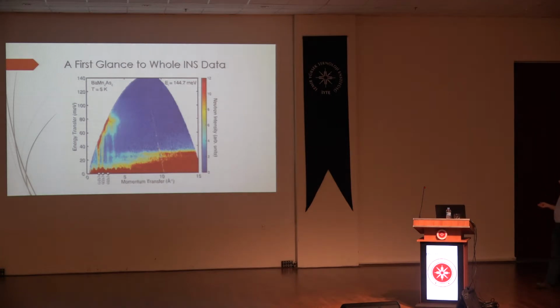First glance at the whole data. The whole data is this. As you see, that is three-dimensional data. This is not a point detector scattering experiment. That is an inelastic powder experiment, where the detector coverage is a semisphere of detectors, so many of them in the 2 theta arm. And once you collect the data, you collect all of it, all possible information over there.